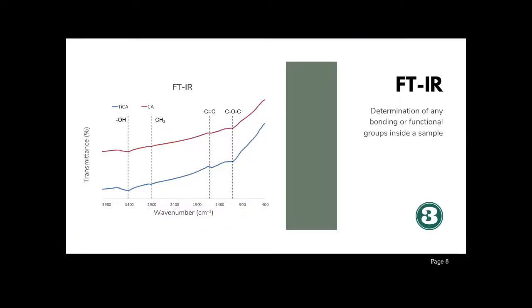We found also from FTIR that both of our carbon aerogels are composed of methyl, ether, and hydroxyl functional groups. Double bonds of two carbon atoms are also identified from the analysis. This is because there are visible slight drops at the distinct wave number of each type of bonding.